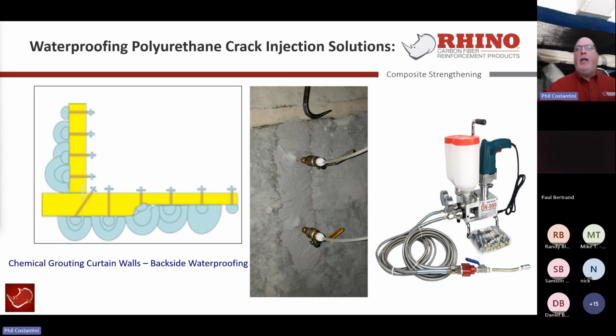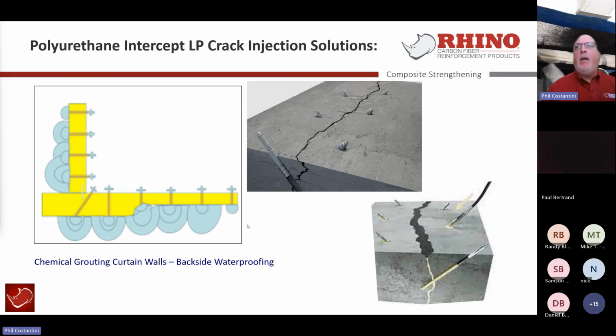You can inject directly into the crack if it's micro cracks or a very minor leak to create what we call a grouting application, or the bigger application, the one I prefer, is what we call the intercept low pressure crack injection solution. So if you've got multiple cracks in any one structure, a wall or a slab, we use these high pressure port fits and intercept the crack, okay, to create what I call a gobby water stop or a grout curtain wall, backside waterproofing to ensure at least close to 100% you're going to stop the water